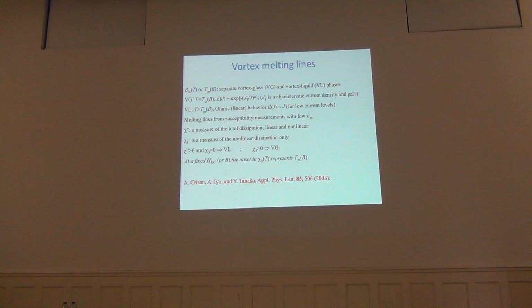vortex melting lines. It is a technique which I developed quite a long time ago for studying some strange thallium and mercury-based superconductors which were made only by a high-pressure synthesis technique. So the story is that we all know that the vortex melting line, Bm as a function of temperature, or melting temperature as a function of field, separates the vortex glass and vortex liquid phase. Vortex glass has a strongly nonlinear dependence of the dissipation on the current, while in the vortex liquid there is an ohmic or linear behavior.